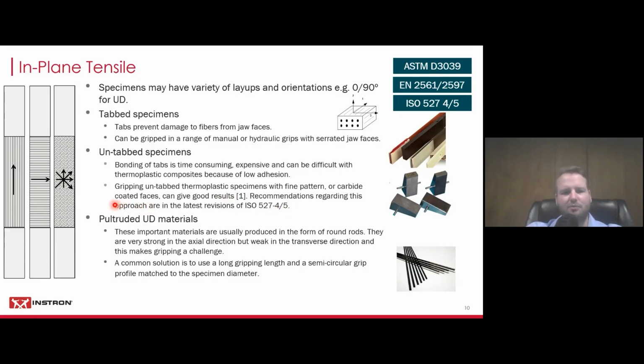And then lastly, here on the in-plane tensile testing, we have pultruded unidirectional materials. They're very important. They're typically in the form of round rods. They're very, very strong in their axial direction, but in the transverse direction, they're very, very weak. Like we established, unidirectional materials have all the fibers oriented only in one direction. So if you start clamping on from the side, that can be difficult and you might damage your material there. So a common solution to that is using a very long grip engagement length. So you try to grip it over a long, long distance and use a semicircular grip profile that matches the test specimen's diameter.